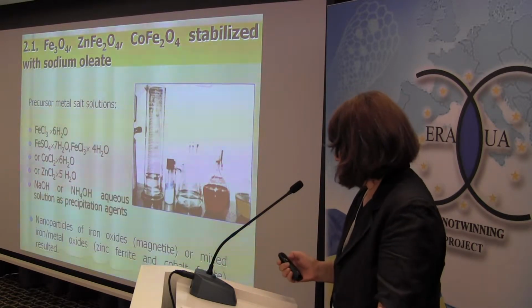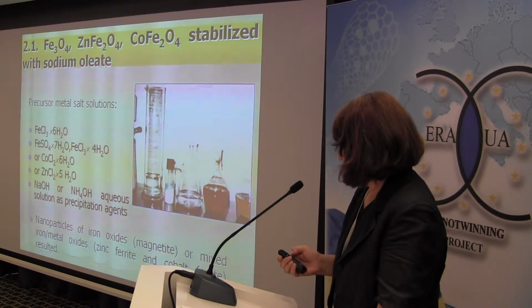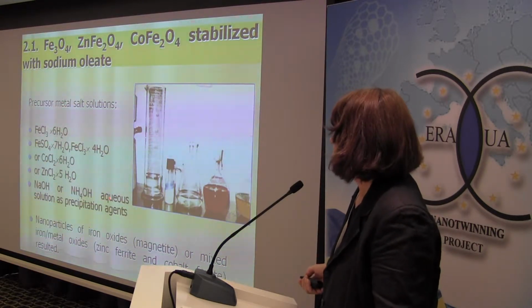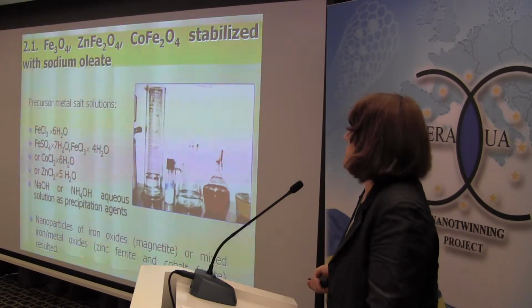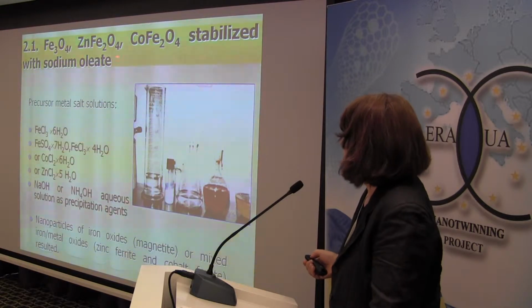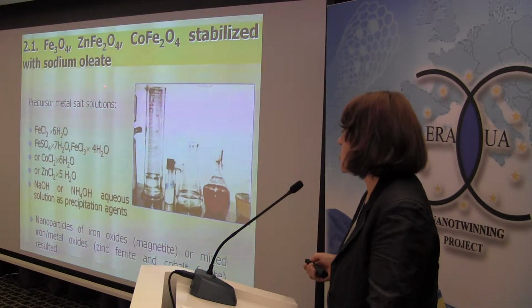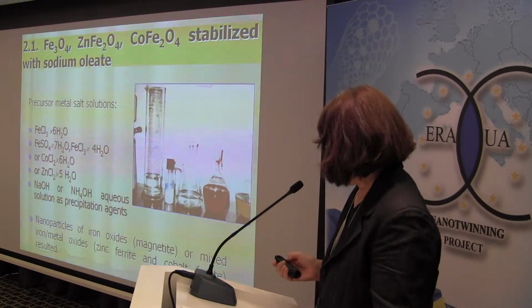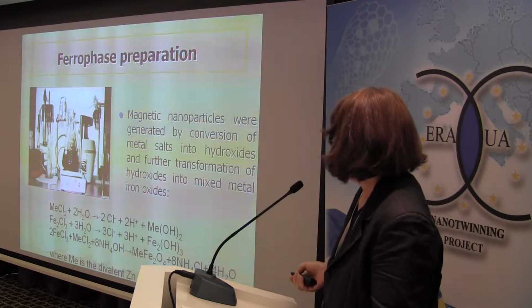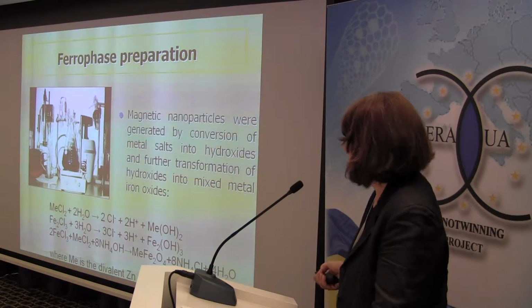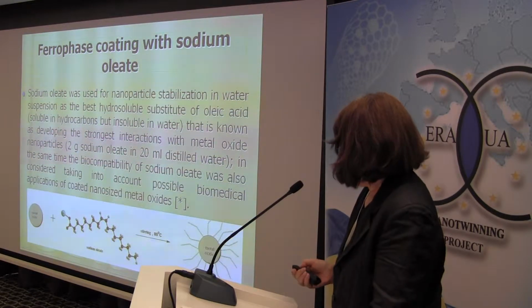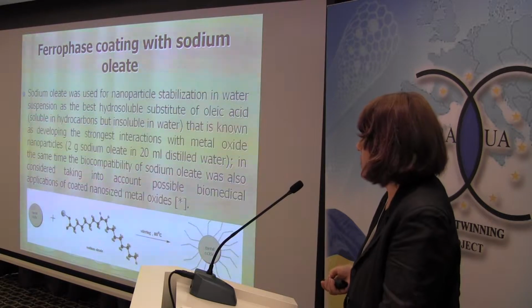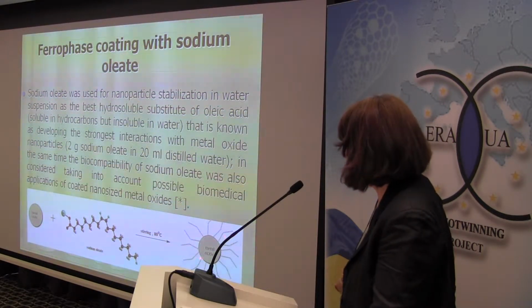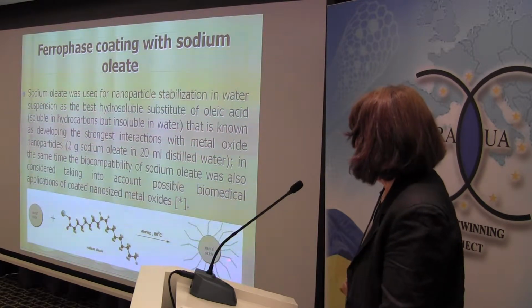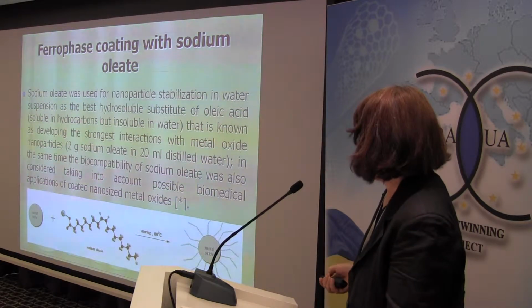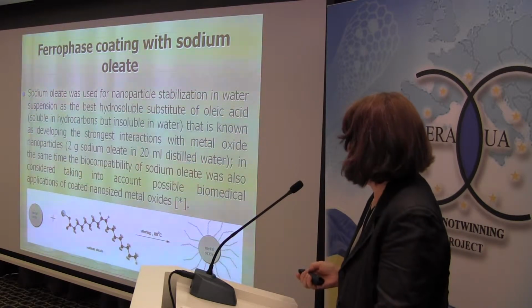The second category of fluids with magnetic nanoparticles suspended within them that we approached are those with an aqueous environment for the final product, not only magnetite but zinc ferrite also, and cobalt ferrite stabilized with oleate ion also, but from sodium oleate, which is hydrophilic, in contrast with the oleic acid, which is hydrophobic, of course. Ferrophase preparation has two main reaction phases: first hydroxides formation and then oxides precipitation. And here is the long tail of this water-loving molecule or ion, the oleate, ensuring a good covering of nanoparticles with this non-magnetic shell, but hydrosoluble and also biocompatible, as some literature data have shown.